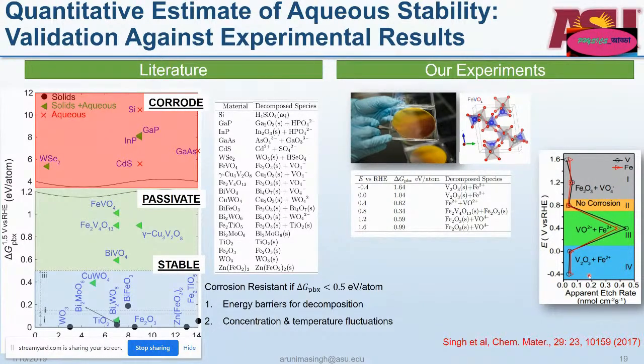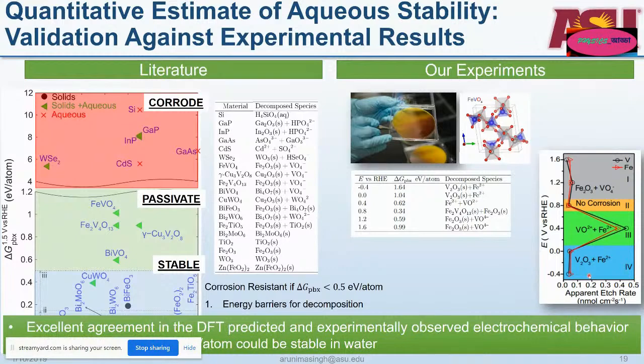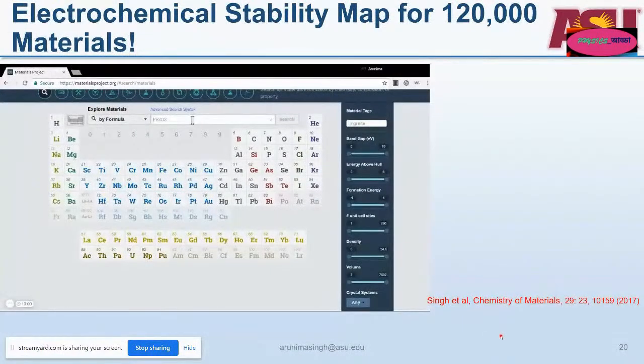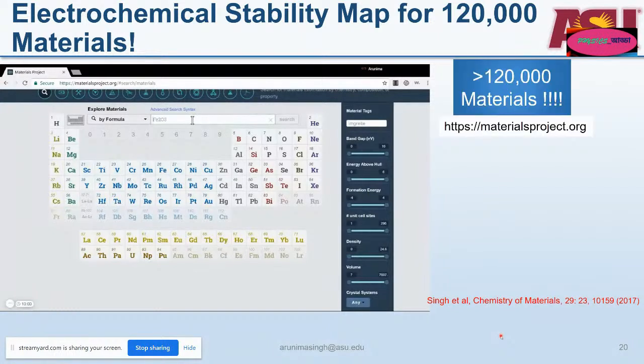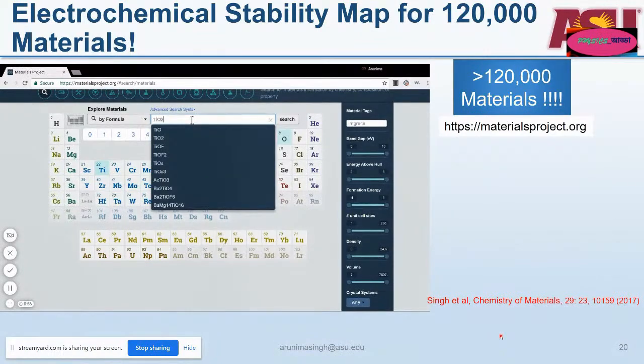So by this twofold validation, we were able to show that our formalism of looking at electrochemical stability maps gave a quantitative estimate for determining aqueous stability. And we found an excellent agreement in the DFT predicted and experimentally observed electrochemical behavior. And this is a very powerful technique. We actually made this technique available on the Materials Project website, not only through the website, but also through their code base. So what you can do now is go to the Materials Project website, enter a compound of interest,